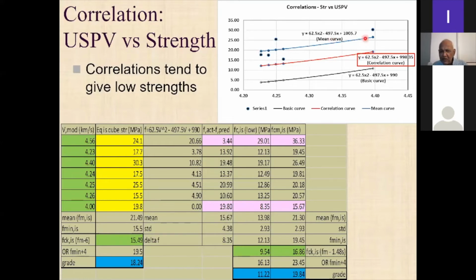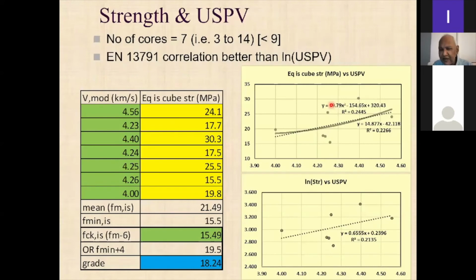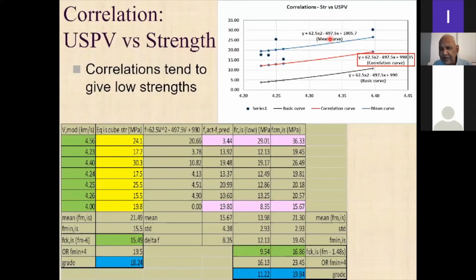Now, if you just fit a parabolic curve like that, you will get different values and different coefficients here, right? But you're not allowed to do that. You have to put this factor there and that factor there, because only that will make it parallel to this basic curve, right? So you get this difference and you do it, but then again, from that, you reduce this one here, right? So actually, I will not go into that, right? But from that, there is a way that you take that standard deviation and reduce it to this actual correlation curve which you get here, right? So it is all given in the code of practice, right? And with a little bit of thought and care, you can get there, right?